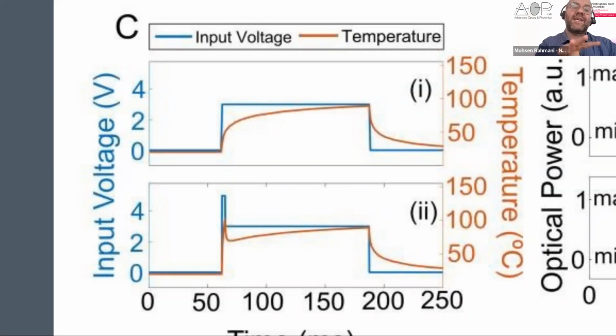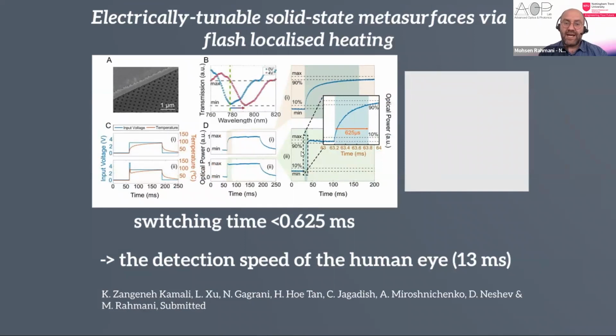It is the first time we are taking this strategy in optics, because this spike, or voltage bias, is something that is done in electronics, but in optical switches it has not been done yet. By using this spike and very sharp increase in the voltage, we could significantly decrease the modulation time. As you see over here, we managed to get 625 microsecond modulation time, which is amazing. I want again to emphasize that our eye can see 13 milliseconds, and with 625 microseconds of modulation time, we are much faster than what our eye can see, and it opens a lot of applications for displays and other applications that are at the moment suffering for optical switches.